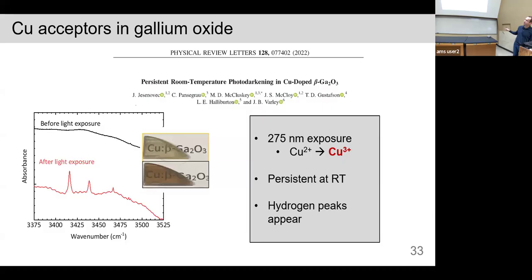Before light exposure, there's sort of a flat absorption profile. These are offset for clarity. And this is showing in the infrared. And on the right is just a picture. So after light exposure, it turns dark, kind of a brownish color. And along with that, in the infrared, we see these distinct peaks that we attribute to oxygen-hydrogen vibrational modes. So just to summarize, exposure to 275 nanometers, we think, turns the copper 2+ into copper 3+, giving it this color. Persistent at room temperature, lasts a couple of weeks. And hydrogen peaks also appear. Hydrogen, once again.